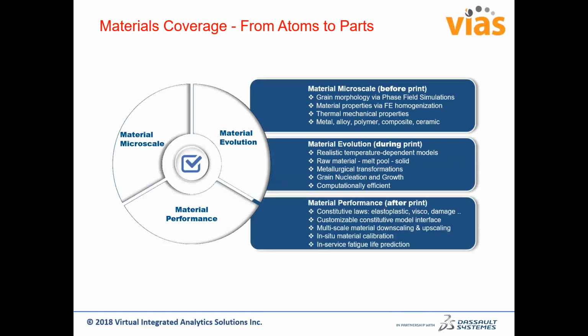Material evolution during print: during print, you have to look at how materials are changing under temperature, and also, due to the thermal process, grain nucleation and growth and all the metallurgical transformations are happening. So your hardness will change. Your thermal field has to be accurately captured to come up with the material hardness in your manufactured part. And then finally, the performance. Once you make the material and put it in situ, there is fatigue life, there is a corrosion effect, there are fractures. All these things can be modeled.